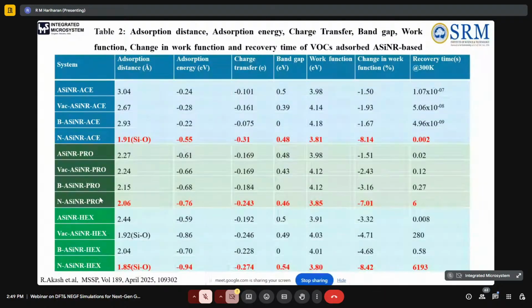Similarly, when it comes to the propanol biomarker, we can see that the nitrogen-doped system has a very good adsorption energy again, which is correlated with the charge transfer as well as the change in the work function. When it comes to hexanol, once again it is the nitrogen-doped silicene nanoribbon which has very good adsorption energy as well as the change in the work function and the charge transfer.